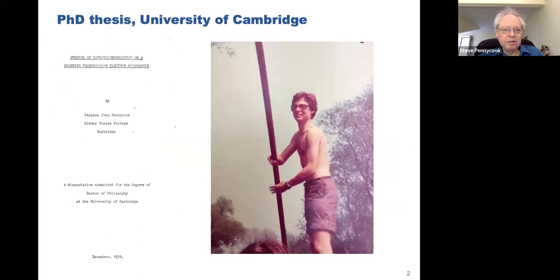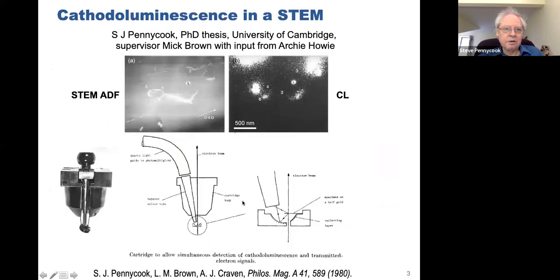And then I stayed for a PhD, and this is really where it all started. Now, my PhD was not about atomic resolution imaging in any way. It was cathodoluminescence in the STEM. What I did was build a little light collection device down around the sample, and you could get STEM images, diffraction contrast, annular dark field images showing defects in diamond, and correlate with light emission. And you can see some are bright, some are dark. Now, I never actually figured out why, because the cathodoluminescence is far more sensitive to impurities than EDX or X-ray analysis, for example, or EELS.